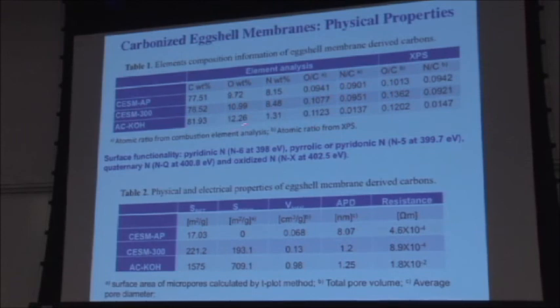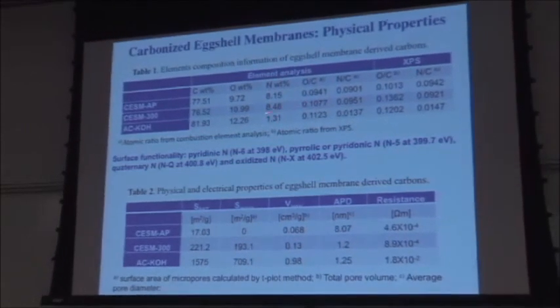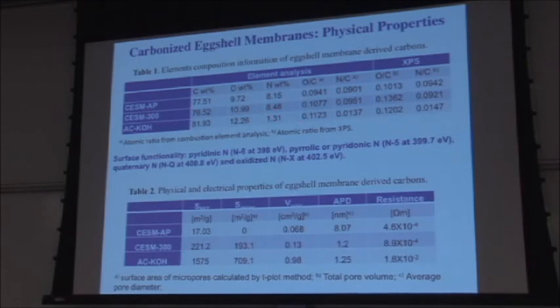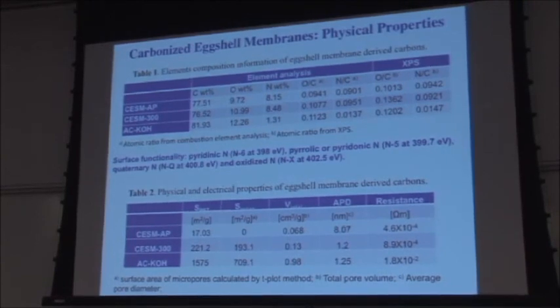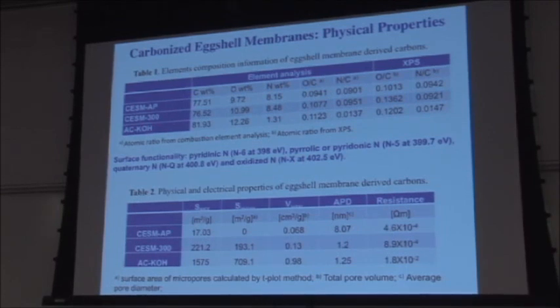And the nice thing about having your nitrogen in your bulk, in addition to your surface, is that during cycling, if you electrochemically dissolve some of the carbon, there's more nitrogen waiting in the bulk of your material. So it's kind of nitrogen all the way down. If you look at the activated eggshell membrane KOH, basically it's low nitrogen content. Again, it very much looks like an activated carbon.